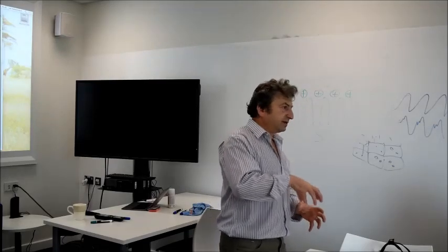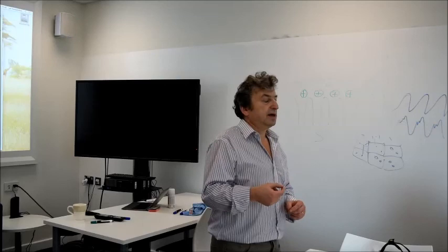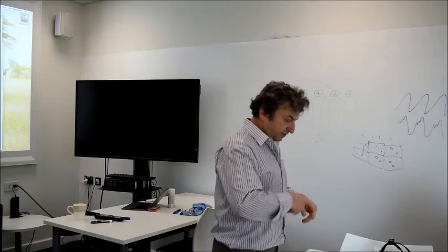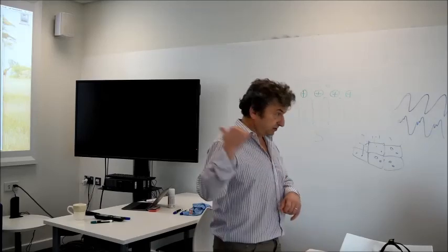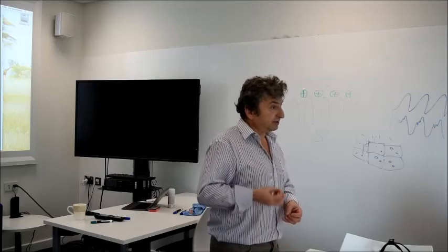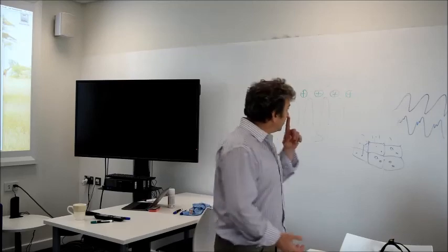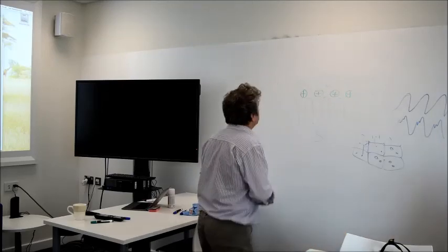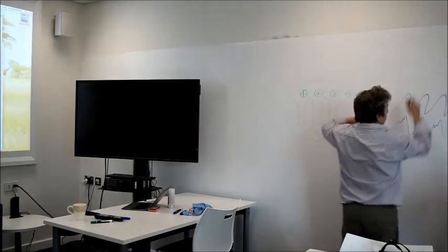So we started, for instance, on an oxygen-terminated copper surface, manipulation of a so-called super copper atom, which is a copper atom standing in a specific position on the surface. And experimentally, it was found that not always this copper atom can be manipulated. And in fact, it jumps on the tip rather than from one position on the surface to another position on the surface, which I presented. You can also take atoms or even molecules on the tip or from the tip, you can drop something on the surface. And we've done also one very interesting paper on this C60, which I can probably explain.